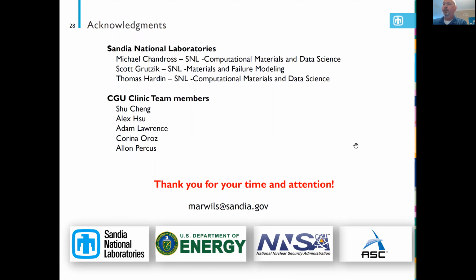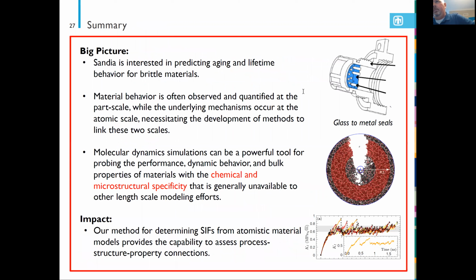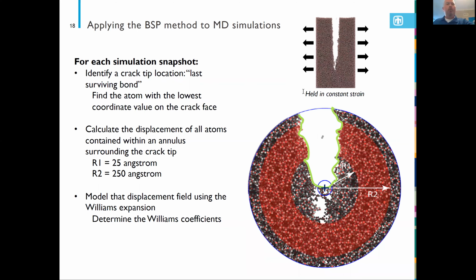Mark, this is Sachi. I have some questions on the results you have, particularly on slide 18. Okay. So you are looking at linear elastic fracture mechanics to derive your properties. It assumes a sharp crack, right? You clearly don't have a sharp crack. And on top of it, you seem to have quite a bit of crack bridging going on ahead of the crack, which is more indicative of what you would see in elastoplastic behavior.